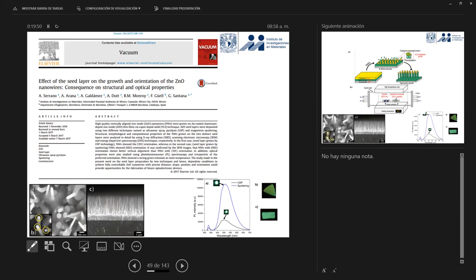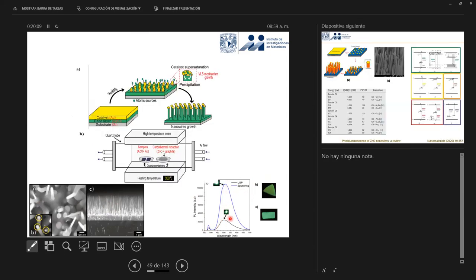When we checked the optical phenomena of these nanowires, we found that they had a very nice emission. You can see the whole sample was emitting in green color. And depending on the growth technique, they had different kinds of emission bands. Here in this case, the intensity was changing. So what was the technique we were using for the growth? This technique is called the VLS growth mechanism.